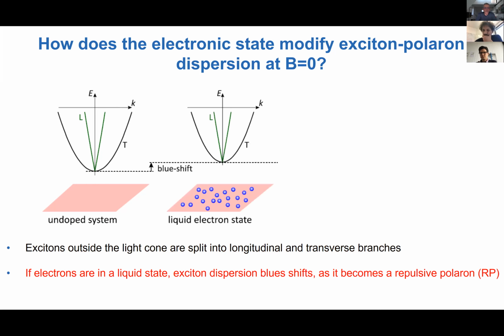Okay, so we normally look at k equals 0, but this is the exciton dispersion of an undoped system. Now, if you put in the electrons, like I have shown you before, and if the electrons are in some liquid or disordered state, then what we see is a blue shift due to the repulsive polaron formation. I'm assuming a constant density, so I move in this plot that I've shown you before. There is a blue shift, maybe some line broadening, but otherwise the dispersion remains the same.